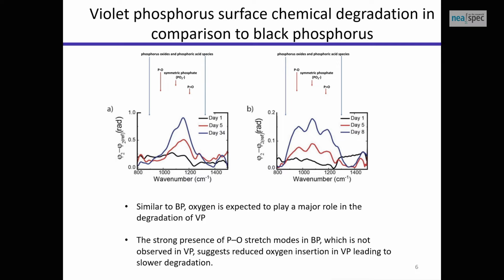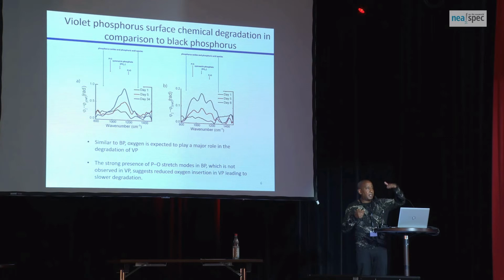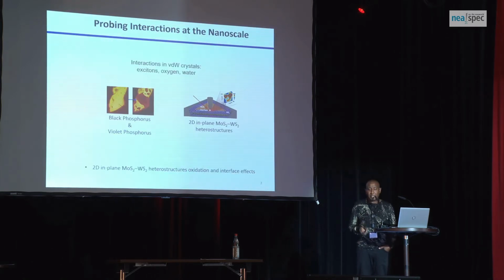And so in both cases, oxygen is important to degrade the material, but it's the strong PO stretch mode in BP, which is not observed in VP, suggests reduced oxygen insertion. We have tried to understand this recently by trying to look at the structure and oxygen diffusion through the material, due to the structure of violet phosphorus being different from black phosphorus as a contributing effect on this. So I'm going to move on into the next one due to time,